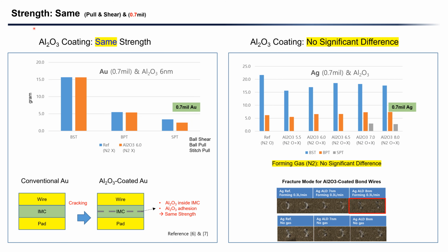Here, for the 0.7 mil gold wire and silver wire, almost the same strength was obtained. Aluminum oxide coating does not change IMC types or IMC thickness between wires and pad metals. The resulting IMC surrounds the broken pieces of aluminum oxide. And aluminum oxide has a good adhesion to wire and pad metals. This is why bonding strength is the same for both no coating and coating cases of aluminum oxide.